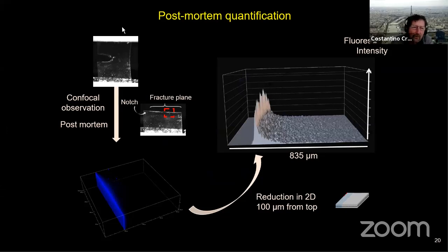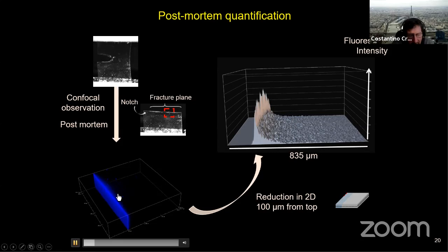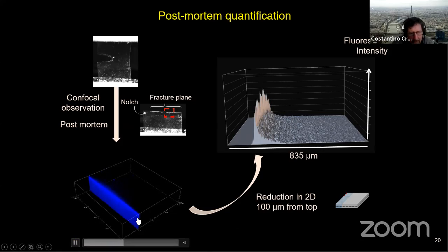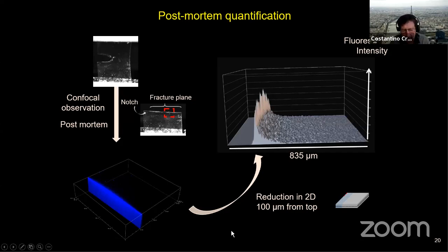So we did experiments of fracture at different rates, with different materials, different temperatures, and we looked at the fracture plane now. So the sample is broken. We are looking at an area where the crack was actually propagating, and we can also measure the propagation velocity from the experiment. Now, this particular image here on the left shows you the activation close to the surface. And I think you can see, it rotates a little bit. So on the left side, you have the fracture surface, and you can see that there is a kind of strip where the bonds are broken.